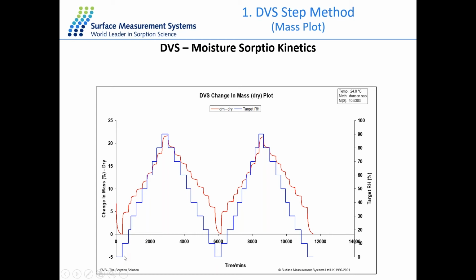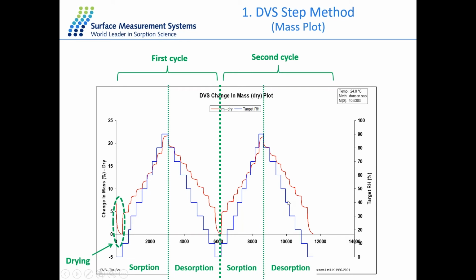So the blue line is the partial pressure of each step, which has the axis on the right-hand side here, the target relative humidity. It's changing from 0 to 90% RH with 10% intervals, and then desorption to 0, and it's a two-cycle experiment, so the first cycle and the second cycle. And the red line is the change of mass for the sample. The drying stage here is just the flow of the carrier gas to the sample to establish the initial dry mass of the material. So that could tell you about the initial moisture content inside the material.